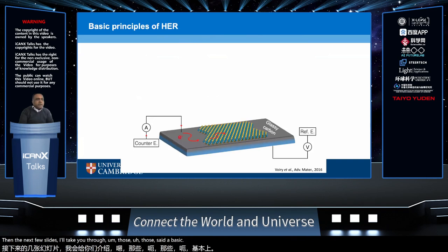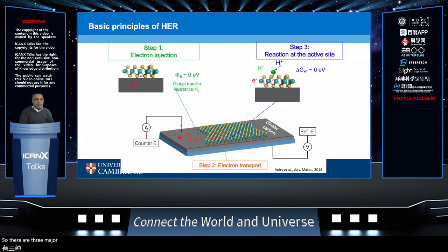So in a hydrogen evolution reaction setup, what we have typically is a host for the catalyst, so a substrate. This is typically glassy carbon on which the catalysts are deposited. And this is typically immersed within an electrolyte, which is usually sulfuric acid. So you have lots of protons floating around in the electrolyte that are used for evolving the hydrogen. There are three major steps in a hydrogen evolution reaction. HER in many ways is a very simple reaction, so it allows us to study the fundamental characteristics of new catalyst materials in a rational and careful way.